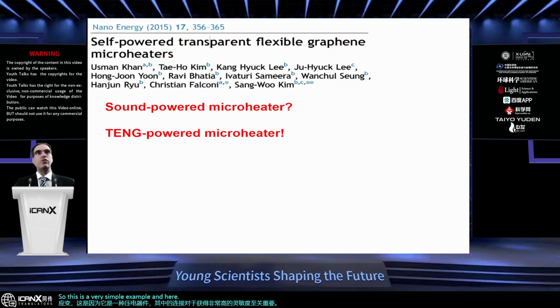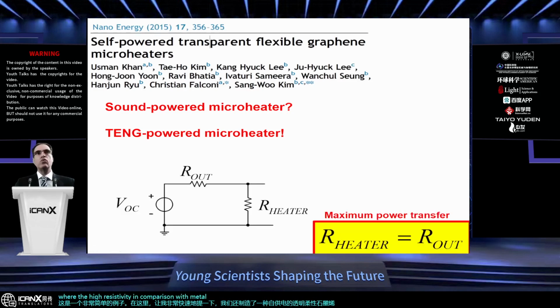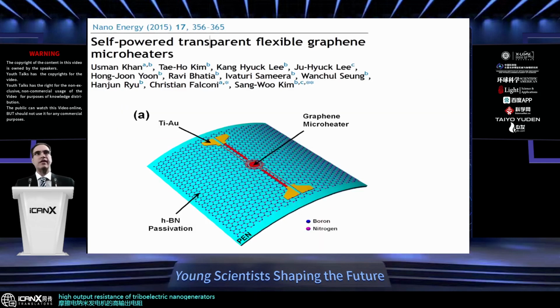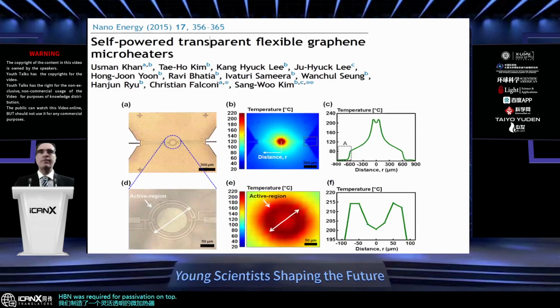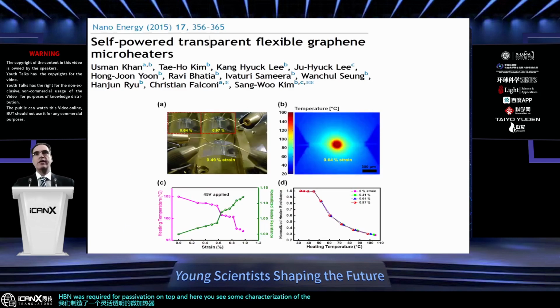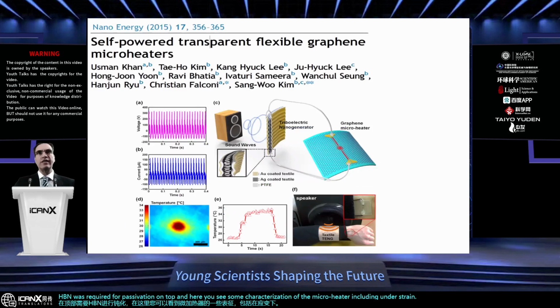And here, just very quickly, let me mention, we also fabricated a self-powered, transparent, flexible graphene microheater where the high resistivity of graphene in comparison with the metal was useful to match, to adapt the large output resistance of triboelectric nanogenerators with the resistance of the heater. With this approach, we fabricated a flexible and transparent microheater. The hBN was required for passivation on top, and here you see some characterization of the microheater, including under strain, and also this is the first sound-powered triboelectric powered microheater. You see, we could power it without any connection to batteries or to other electronics.